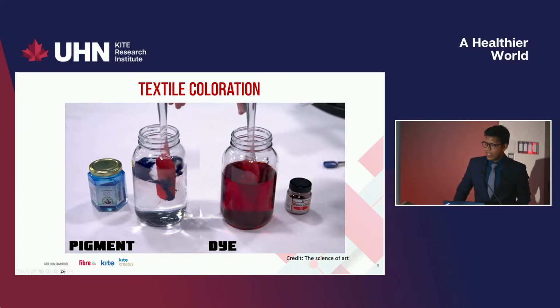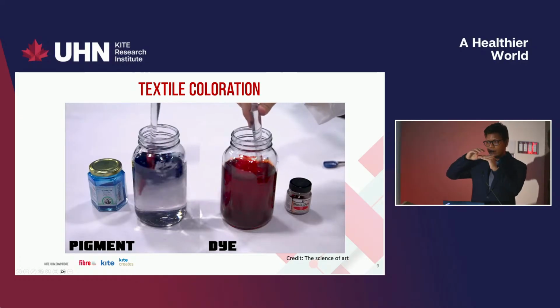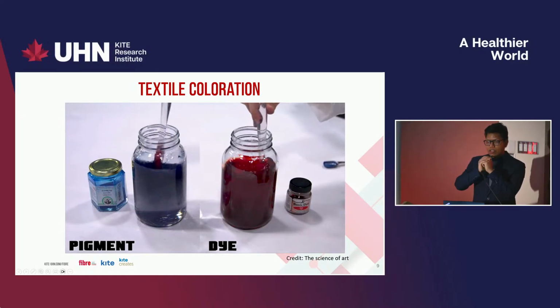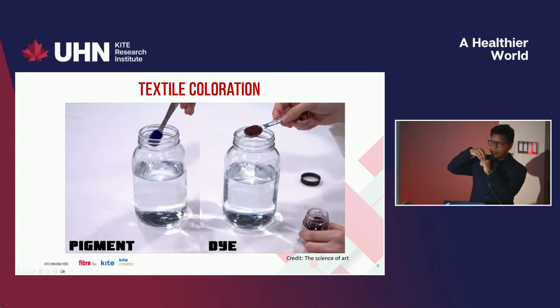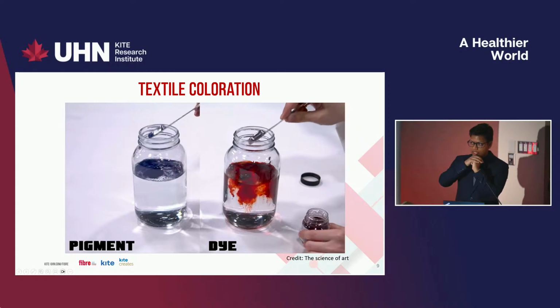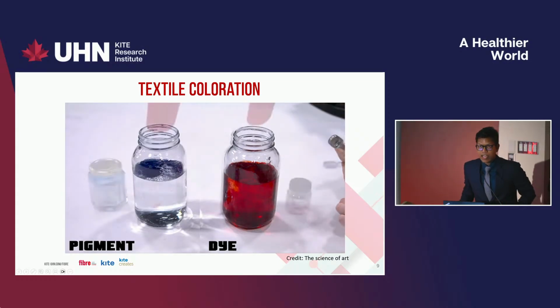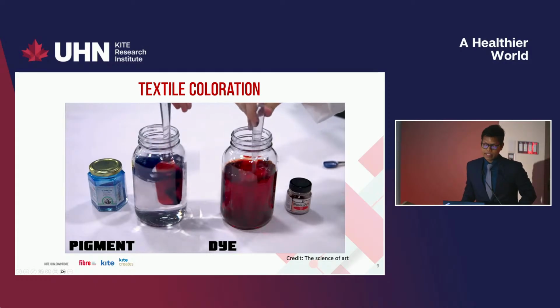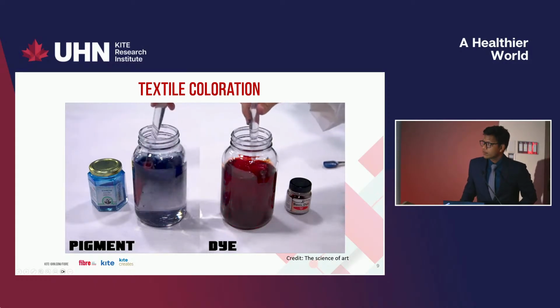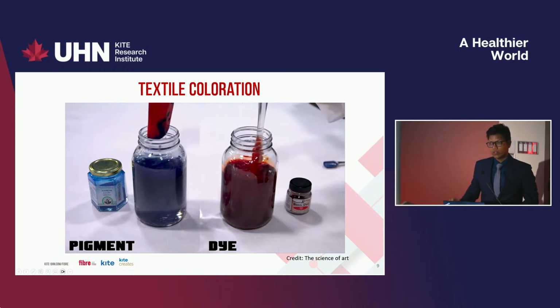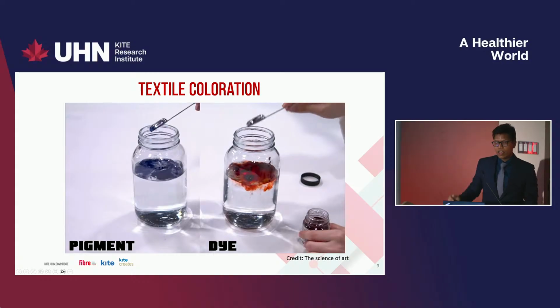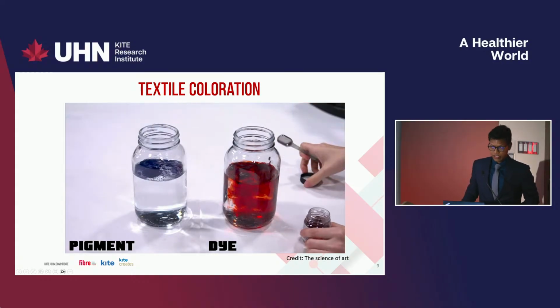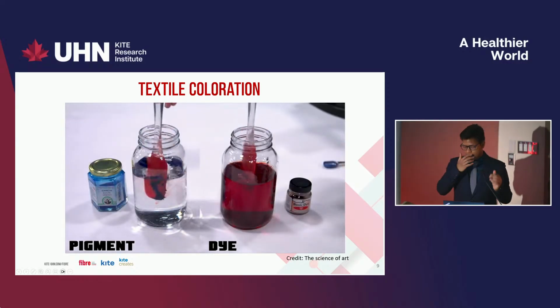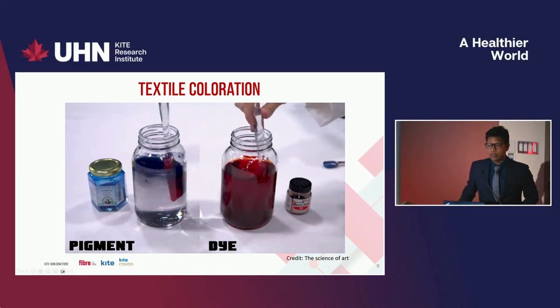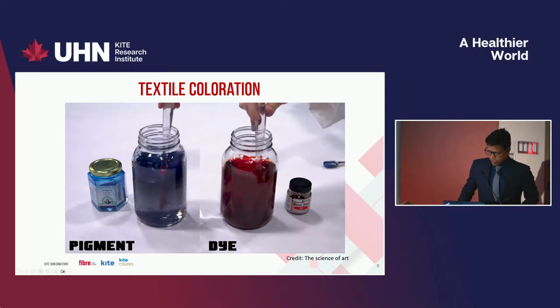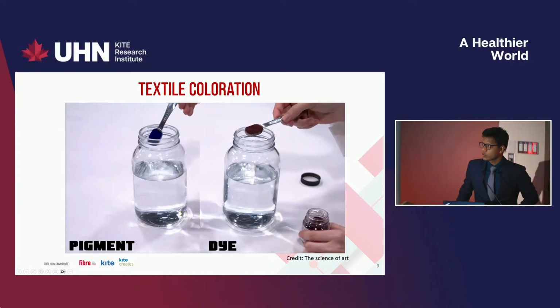On the other hand, as pigments are bound to the fabric with adhesive or binder, only a tiny surface area of the pigment is exposed to light. And I was mentioning this in my previous session as well. Light is a crucial factor to degrade your fabric. So as pigments are typically large particles, and also the whole pigment is not exposed to the light, you have less chance of light degradation on the pigmented material. So when you talk about textile, there is always a trade-off, but according to the end use we are aiming for, we try to choose which particular product is good for us.